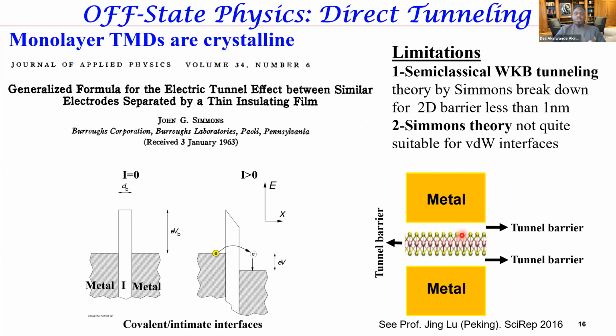So what that means is when you're applying theory to model these devices, you have to take into account these additional tunnel barriers. Indeed, there are now several papers that have estimated what this gap is for different metal combinations with different TMDs. In the case of MoS2 with gold, this gap, the sum of the top and bottom gap, is actually commensurate with the thickness of the material—so it's a non-negligible gap. When you take into account this gap, this correction effect, you can now actually begin to get the kind of current densities that we observe in this monolayer sandwiched between metal. So we became satisfied that this could be explained.